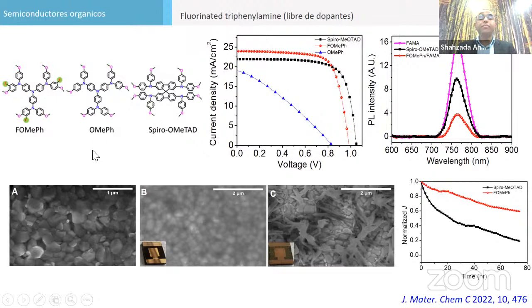They would use two of them. Without fluorine, they form big crystals, and there was no uniform deposition. But with fluorine, there's a uniform deposition. It forms a very good uniform layer. And in the dopant-free state, without any doping, it shows very good performance. And this way, stability was improved.